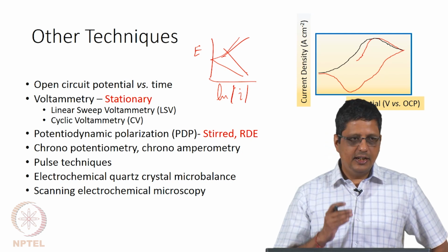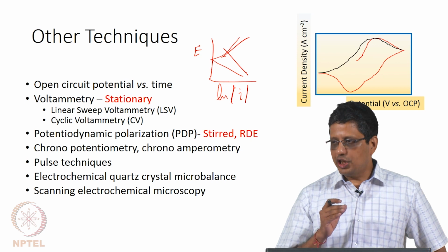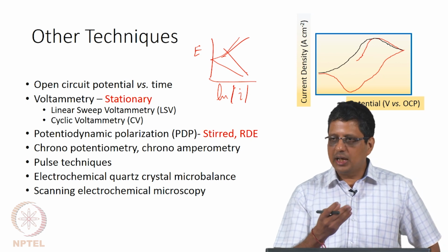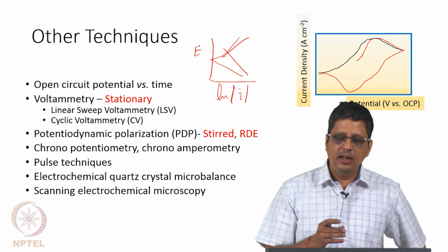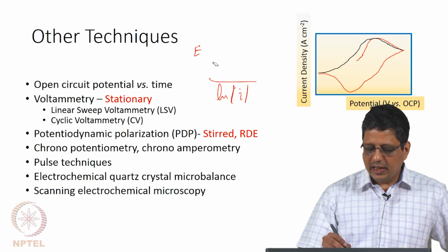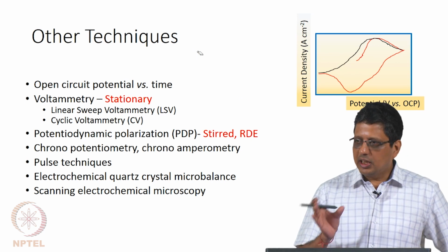If you have a significant corrosion current, significant current from the reaction, large current from the reaction means very fast dissolution, then you might be able to go at a slightly faster rate and still get the correct results, because still the double layer capacitance will not contribute that much current to the final value. So, we have for example done experiments at 2 millivolts per second, that is going to shorten the experimental time